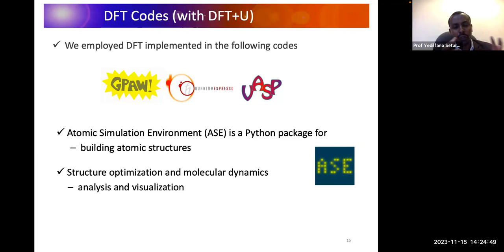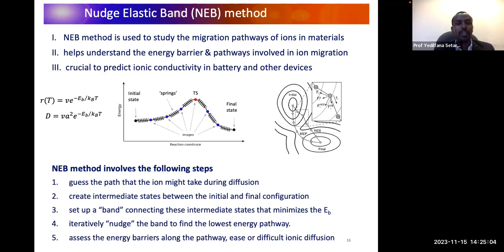building the atomic structure and also for molecular dynamics, analysis, and visualization of the crystal structure, we use the Atomic Simulation Environment software, which is a very user-friendly software. Another important thing that I want to mention here is the method. The method we use to study ionic transport in battery materials is the nudged elastic band method, the NEB method, which is within DFT, and it's really a very good approach so far.